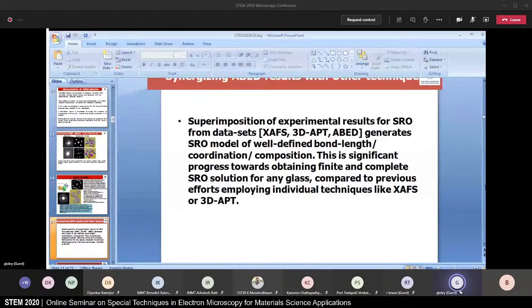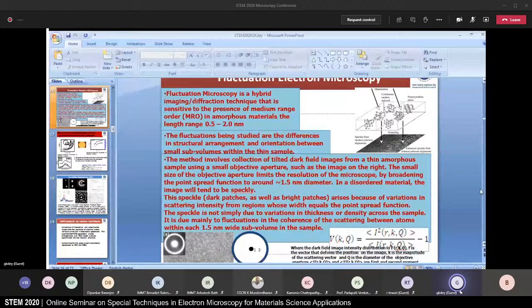Having moved from short range order, we now come to medium range order. And for medium range order, again, we have used a transmission electron microscopy based technique, which is again not very old. This is known as the fluctuation electron microscopy, where we make use of the diffracted intensity from clusters, medium range order clusters in the glass, and you get a diffracted beam, which is very feeble in intensity.